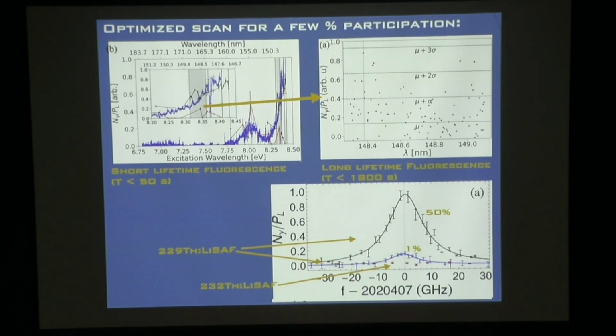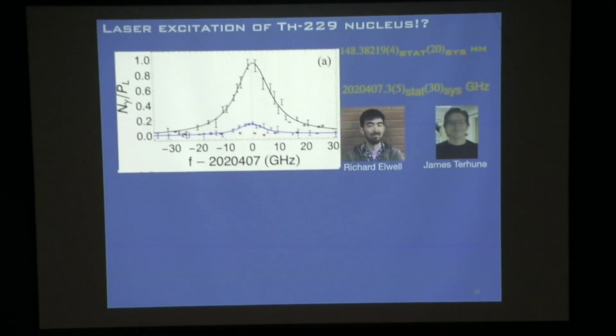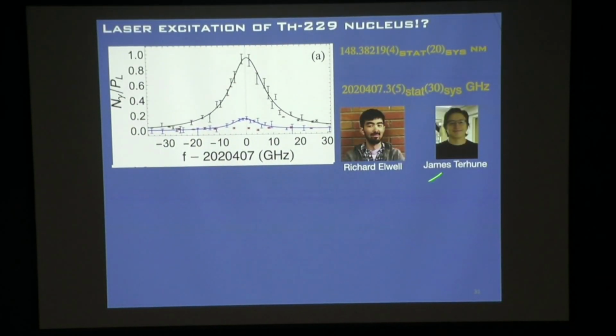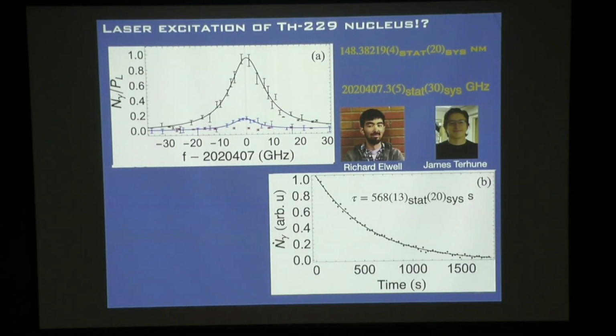And so this is pretty exciting. It looks like the nuclear transition. We were then able to really drill down on the frequency. It's 2,020,407 gigahertz. I'll remember that number hopefully forever. We can then go here and measure the lifetime, this long lifetime. We see something about 570 seconds. We've measured this better now, and it's about 570.